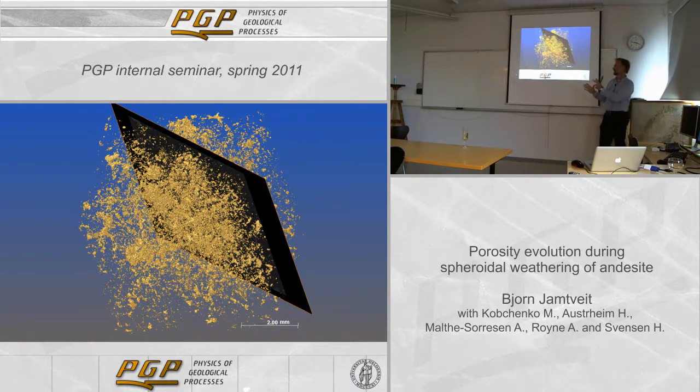So we then tried to look at things in the microscope and look visually where we can actually see the pores, to make sure that we don't overrepresent porosity or lose pores if we don't need to lose. So this is kind of an evaluation based on common sense, basically, where you actually put the threshold in the end. But these are pores, and we're quite convinced that most of these are actually real pores, and you can see that some of the pores are quite big, up to 200-300 microns, just as we saw in the electron microscope, where we saw these rounded bubble-like pores, and many small ones.